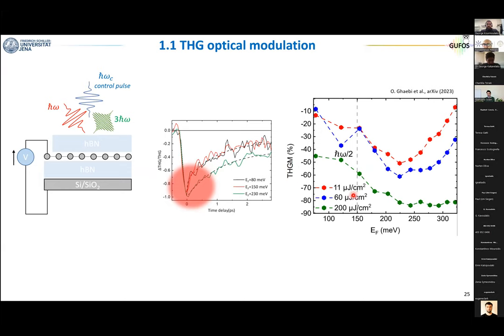Then if you increase the pump fluence or the fluence of the control pulse, of course you change the maximum modulation depth. But the maximum modulation depth is also a function of the doping or the Fermi energy. And I just want to point out that this is highly nonlinear. This can be fully explained if you consider the nonlinear response of the material. But I want to point out that you can reach very large values of modulation, up to 90%, if you go to large values of the Fermi energy and sufficiently large values of the fluence. Okay, so for the third harmonic, we have a full control.